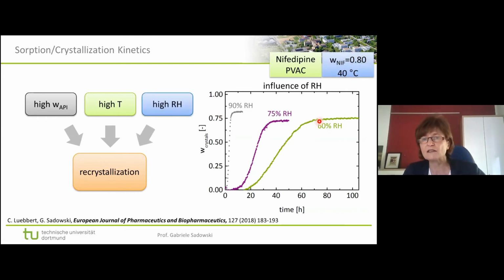And then you see, as this is 60, 75, and 90, what you see is, again, what we saw already from the phase diagrams before: the higher the relative humidity, the higher is the supersaturation. This is one point, and the other is the lower is Tg. So both of these influences go, so to say, in the wrong direction. And that means high relative humidities are really something we should avoid if you want to have a stable ASD.